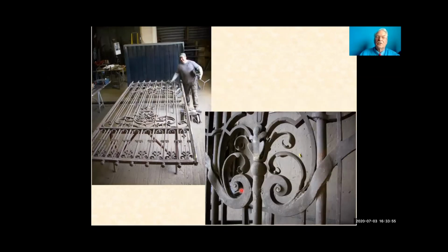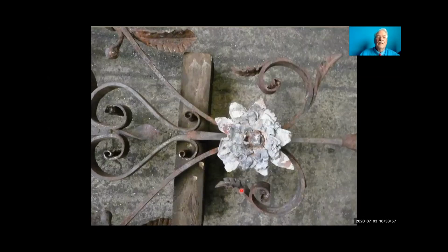Another advantage is that sometimes you don't realize that the decoration is actually not ferrous. This is copper, and there's a bit of lead in there as well. And these wouldn't have survived if you'd used a more aggressive process than chemical dipping. So it has its advantages, it has its disadvantages, and the main disadvantage that I worry about is what's happening to the residue of these very low viscosity chemicals.